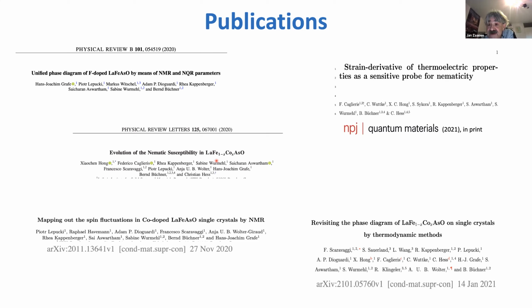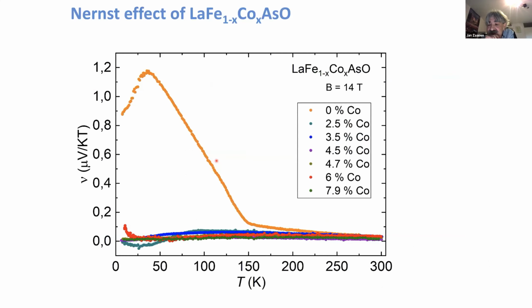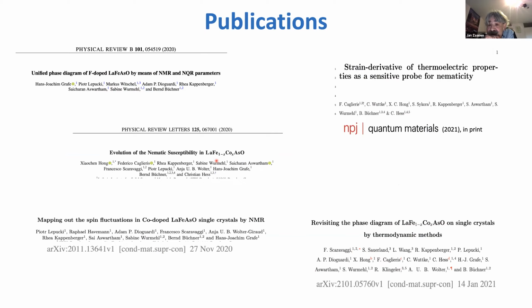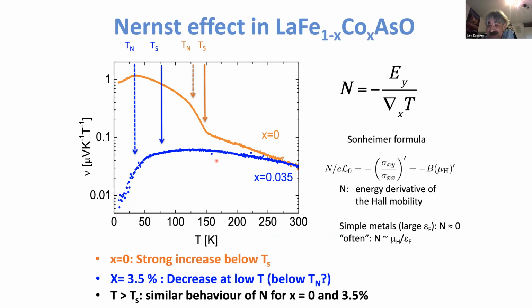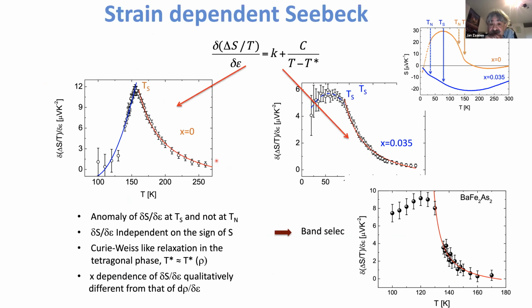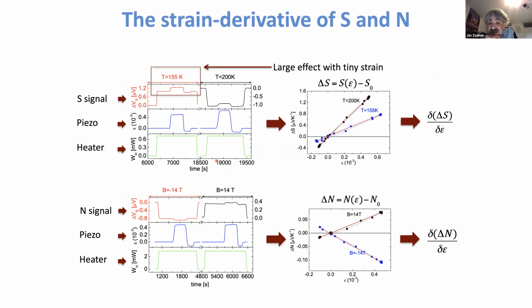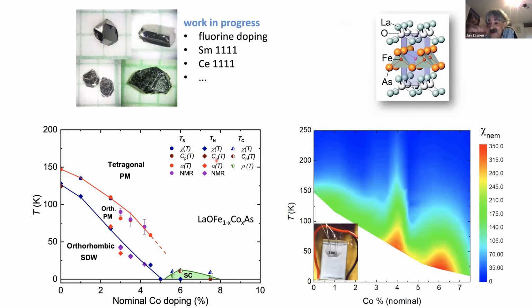And then when you have the first order transition and the lattice is coupled in, the lattice is talking in a very different way with this order than the electron system is doing. Right? The electrons are kind of self-annealing things. Right, so could it be that this sort of disconnect between the neat and orderly behavior of the nematic susceptibility contrasted with this very disorderly behavior of the orthorhombic transition is just about this, turning into a first order transition when the lattice starts to feel the nematic susceptibility.